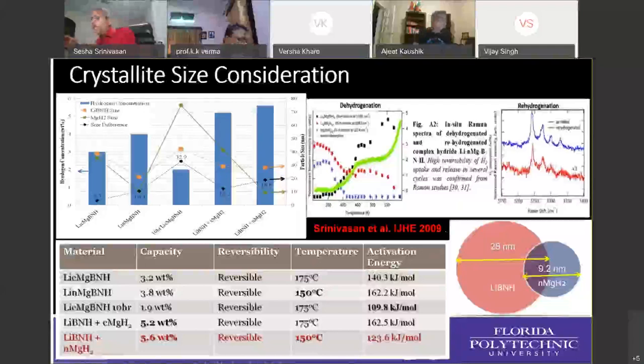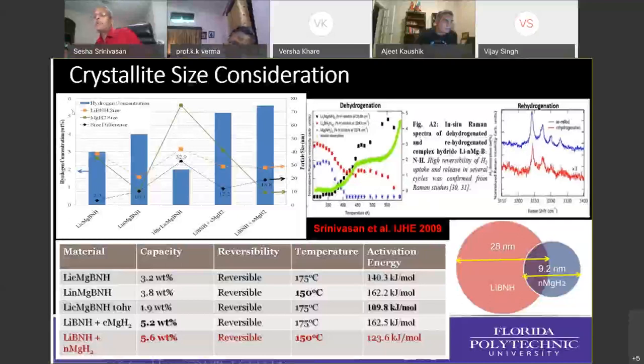What you see is that we did a systematic X-ray diffraction for all the five different materials and then put it in an Excel chart to see these materials' hydrogen concentration with the particle size. If you go with the particle size reduction, I have a little window. On your right, you see 28 nanometers of one component and 9.2 nanometers of another component. If they have a certain particle size, then I can improve my storage capacity or any other property. So my goal is to decrease the activation energy and increase the hydrogen capacity by doing the particleization or nanoparticle formation.